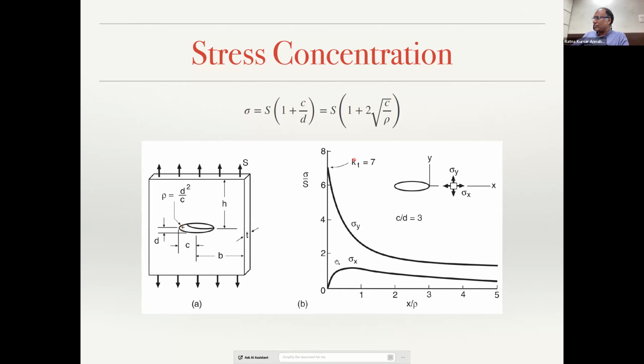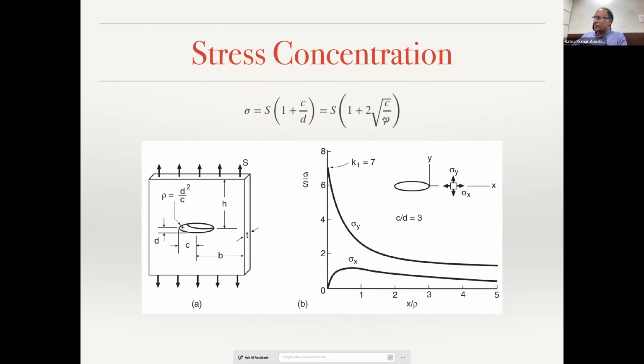What is the radius of the crack tip? It is the curvature of the crack tip. If you plot the stress concentration factor, that is sigma by S, on the y-axis, and x by rho, the position, on the x-axis, at a given position, what is the stress? Far away it should be equal to the applied stress, but near the crack tip it is going to be 7 times, depending on the value of C by d being 3: 2 threes are 6, and then 6 plus 1 is 7. So the stress concentration factor is 7. That means, although in the far field you have applied only 100 MPa, here you will see 700 MPa. That could be much beyond the ultimate strength of the material, and hence you need to be concerned.